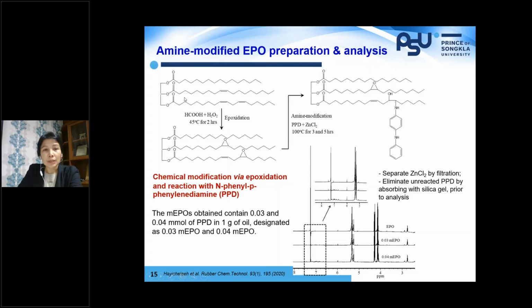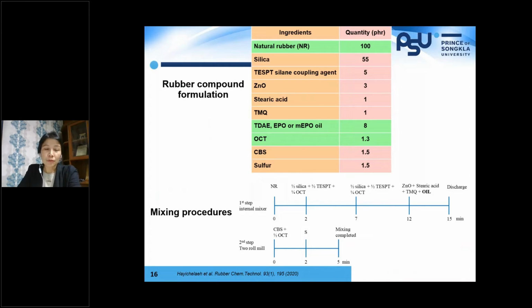And we took one of the EPO and did some further modification by introducing phenyl-p-phenylenediamine, or PPD, here. The reaction was done at 100 degrees using zinc chloride as catalyst, and we obtained two different levels of PPD grafted on these oil molecules, characterized by NMR. So it proves that we have done the reaction successfully. Then we used that modified oil in our rubber compound. Here we compare the modified palm oil with TDAE, and we also have the one without oil as the control. The mixing procedure follows this two-step mixing.